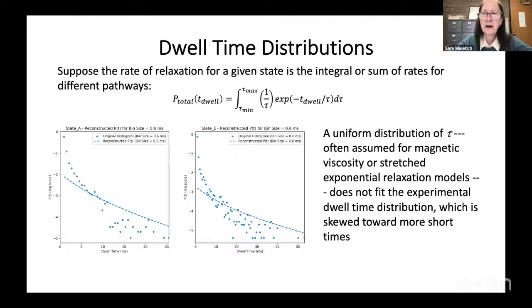And I want to point out, one of the interesting things that's come out of this work is the ability to differentiate from a uniform distribution, which is what has been assumed in all prior magnetics models of what's called magnetic viscosity. So, for example, if you have magnetic relaxation of an ensemble of identical monodomain nanoparticles, Louis Néel said the magnetization will decay with a single exponential.